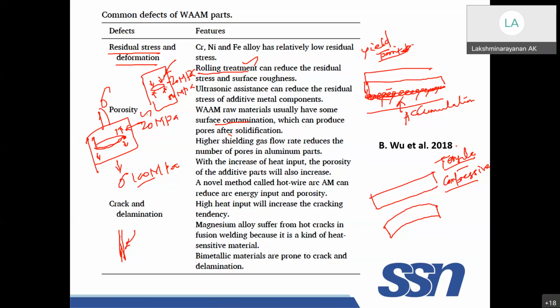What people suggested is a novel method called hot wire arc additive manufacturing, which will reduce energy input as well as porosity, because whatever hydrogen atoms are there will just go away when you use hot wire. That's one of the reasons you can reduce porosity.